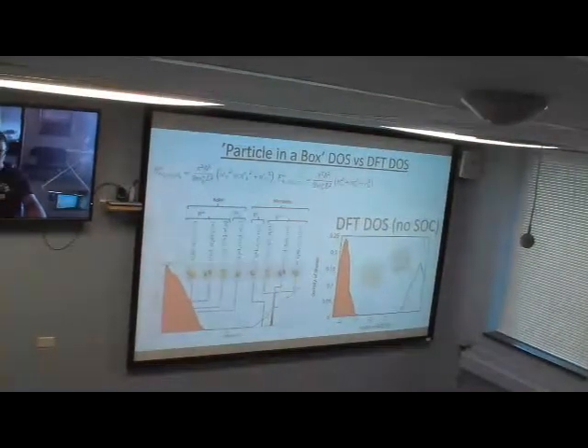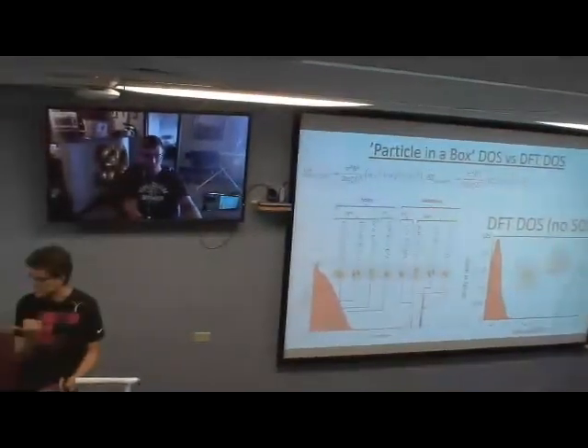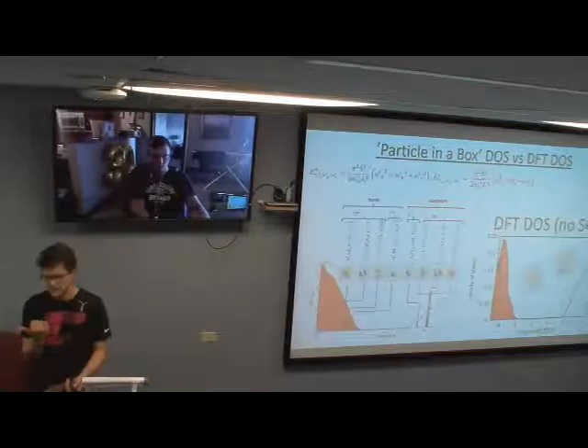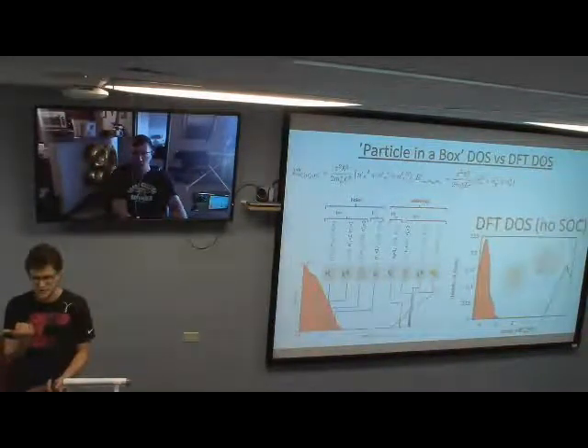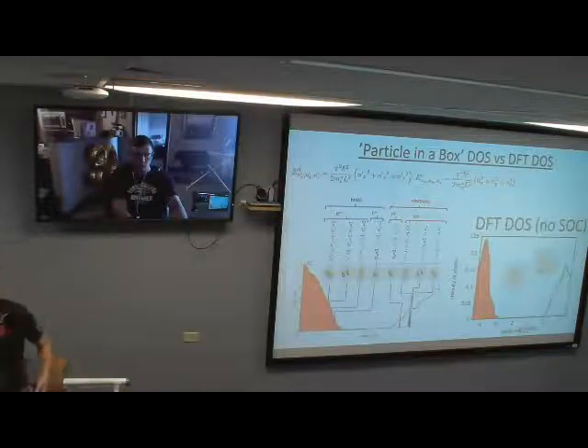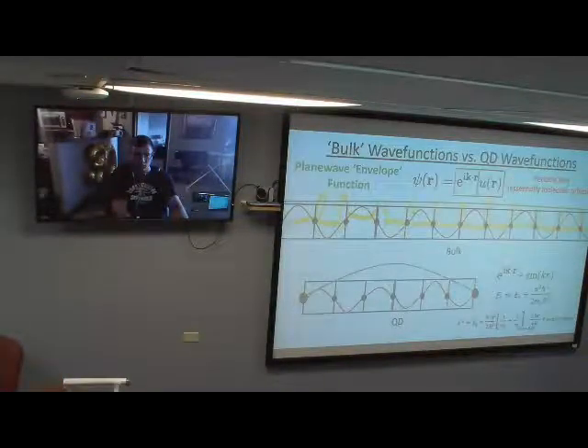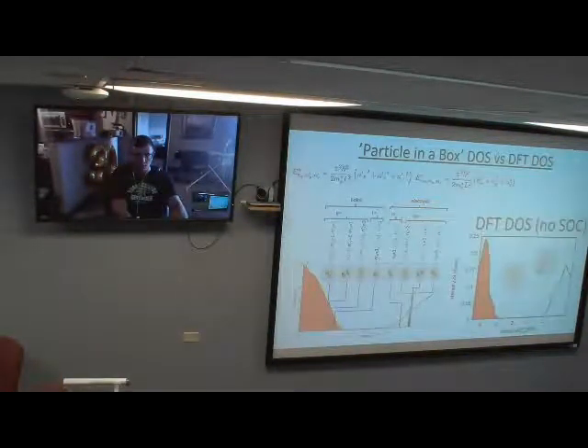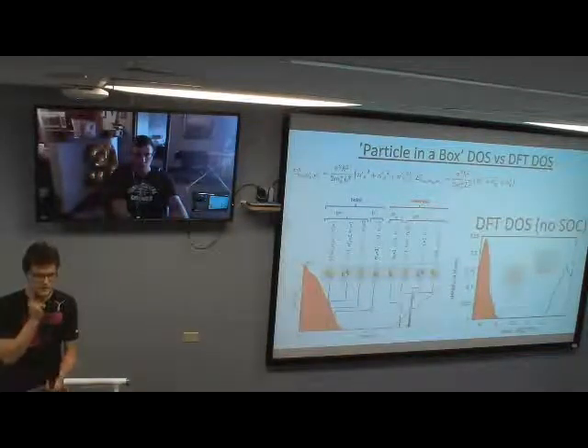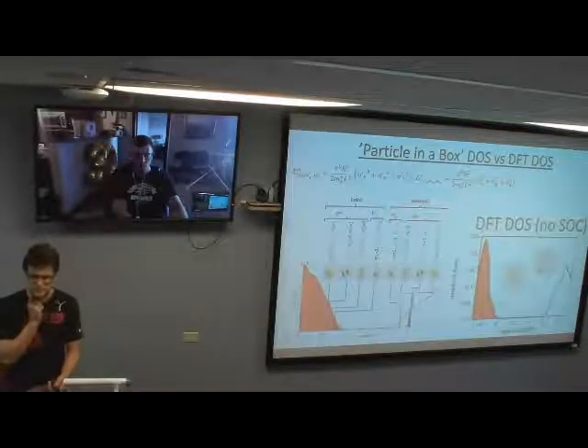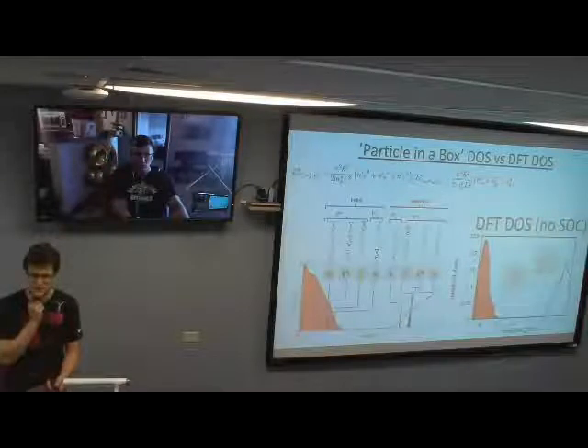Mm-hmm. Because it's kind of on the left side, bottom side, rather than spread over the entire system, right? Yeah, but I've seen other people have computed orbitals for quantum dots that didn't have ligands attached to them, and some of them still have the same feature of the LUMO going across two of the bands. So it seems to be a consistent thing that shows up in these calculations. I don't know if they use VASP or not.